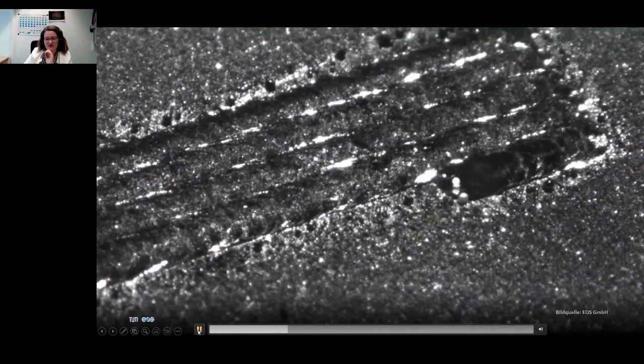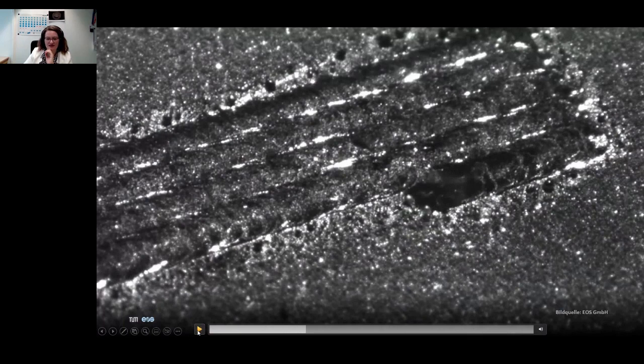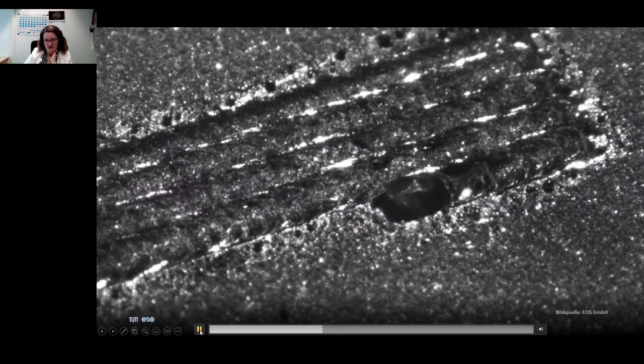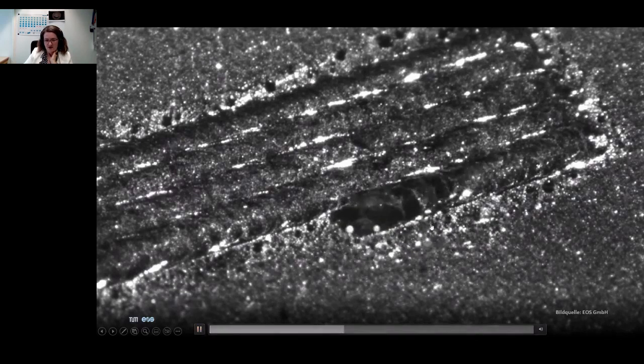The production speed in this case, so the scan speed, was not higher, but maybe you see it, the exposed area is bigger than a typical Gaussian beam profile. A typical Gaussian beam profile has a spot size around 80 microns, and we have here a spot size which was bigger.